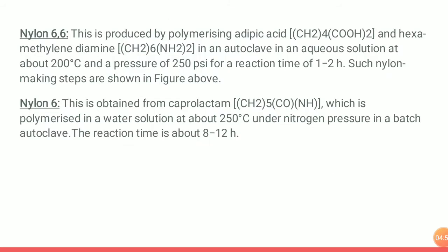Okay, nylon 6 is obtained from caprolactam, which is polymerized in water solution at about 250 degrees Celsius under a nitrogen pressure in a batch autoclave. The reaction time here is about 8 to 12 hours.